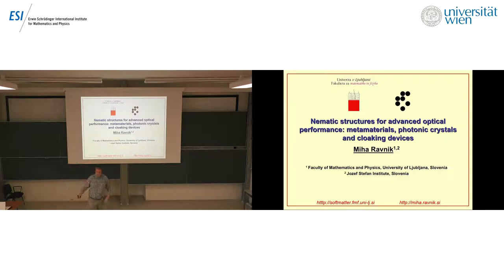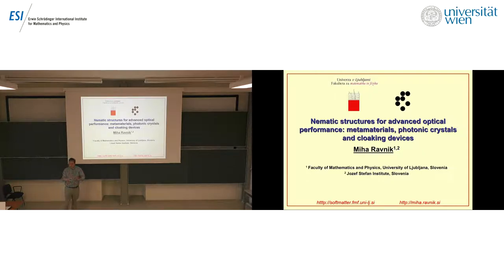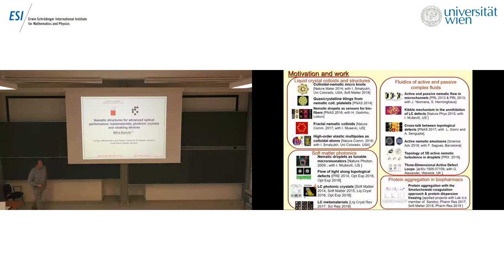The other thing is the spatial response. The pixels in our displays are at scales of about 10 micrometers, but we can design liquid crystal films or patterns which go far below those scales. We can design the orientation of a liquid crystal at scales of 100 nanometers or that order of magnitude — several orders of magnitude below where we work today. This range of liquid crystal material is not yet exploited, and I think there's potential there. This is why I mention photonic crystal metamaterials — applications where you design liquid crystal patterns below the wavelength of light.